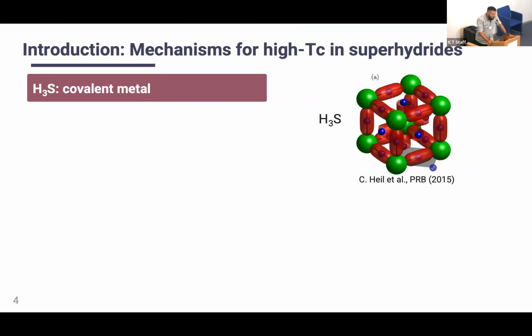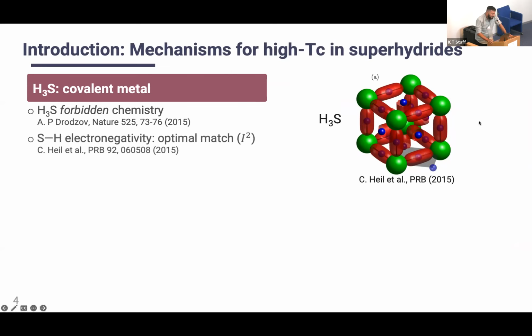The first class is the one of H3S, which is essentially a covalent metal. Now, what we have to think of H3S is, first, that its stoichiometry is not what we would expect from the chemistry we know. We would expect H2S. So we have a forbidden chemistry that also makes our system a good metal, despite the fact that sulfur and hydrogen have directional and covalent bonds. Now, in H3S, we are blessed by an optimal match of the electronegativity of sulfur and hydrogen, which is almost in the best possible spot to maximize the electron-phonon matrix element. And also, we are very close in energy to a singularity that boosts the density of states at the Fermi level. The result is indeed the very high TC.